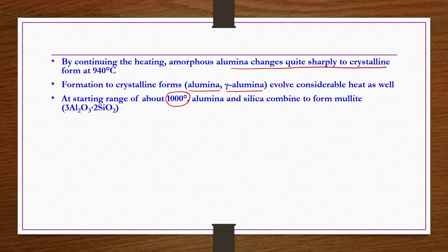So at 600 to 650 degrees centigrade, what happens? Mostly dehydration takes place, plus formation of the amorphous alumina and silica may also take place as per the phase diagram, those things we have seen. But if you further increase the temperature to 940 degrees centigrade, what are you getting? You are getting a crystalline form of alumina. If you further increase the temperature to 1000 degrees centigrade, what happened? Alumina and silica combine to form mullite.